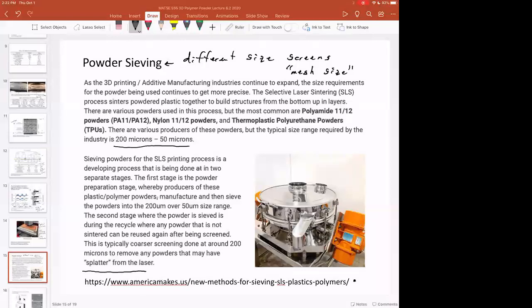recycling polymer powder. And so in order to recycle powder, you may have pieces of powder that aren't necessarily sintered onto the part, but still end up in the bed, because you get this phenomenon called splatter from the laser. So when you're shining a laser very quickly across the surface of this powder, you can have some powder that's ejected, or you can have some powder just right on the edge that's sort of sintered off to the side. And so getting rid of these splatter particles that are sort of fused but not part of the part is important in order to be able to reuse the powder.